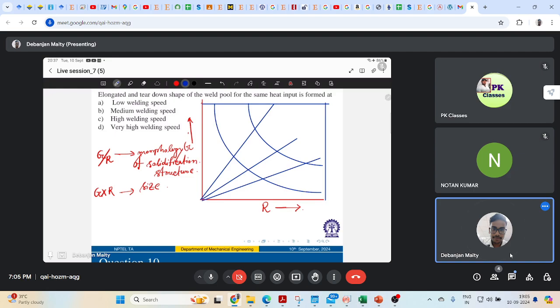So over here, this region in the left side, you will have high G by R, right? So at the topmost region, you will have the maximum temperature gradient and lowest solidification rate. So this region is high G by R ratio. And let's say this region is low G by R ratio.